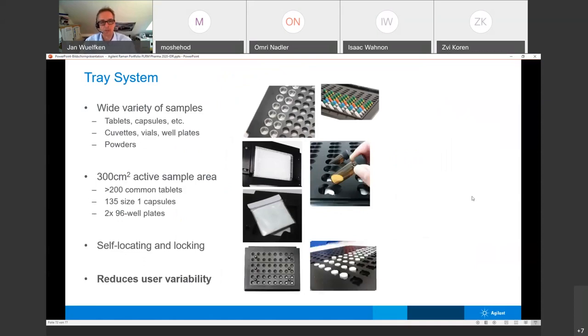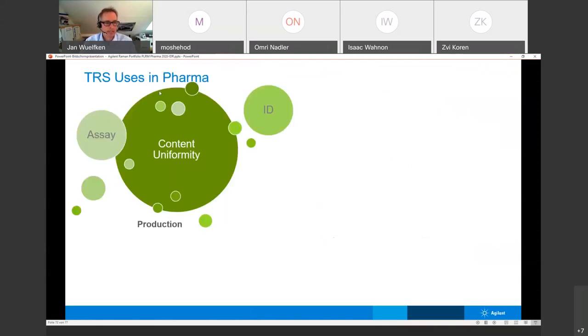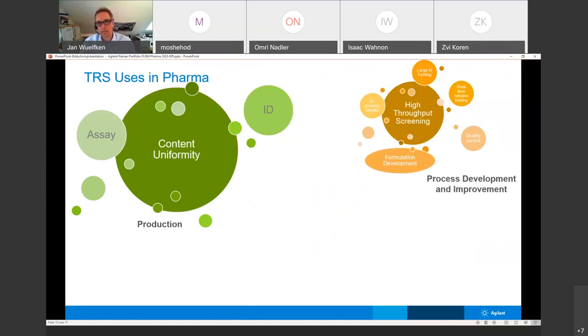And for this variety of samples, of course, we have a variety of trays. If you have a specific size of tablet, we make your own tray fitting to your tablets easily. This is quite often used, so the customers are getting their own trays. You have 300 square centimeter active sampling area, so you have a lot to place here. As I said, mainly content uniformity testing inside of production is the key thing. Of course, when you have a lot of samples, when you have high throughput screening, the advantage of measuring, let's say, 10 seconds for one tablet without any liquids, in comparison to maybe 10 minutes on a UPLC, is a significantly faster way.